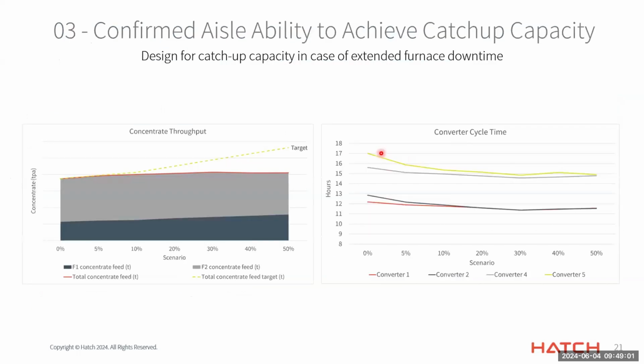So Zimplats also requested additional flexibility in the plant design to accommodate catch-up capacity in cases of extended furnace downtime. So the catch-up capacity was incorporated in the new furnace design, and then the model was also employed to determine if this could be achieved from a logistical perspective. So the 2 graphs show the impact of increasing the concentrate feed rate from nominal rate for furnace 1 and furnace 2 on the annual concentrate throughput and the converter cycle times.